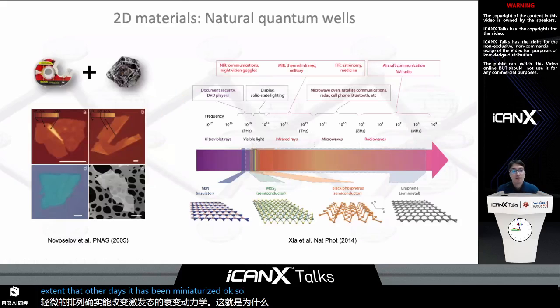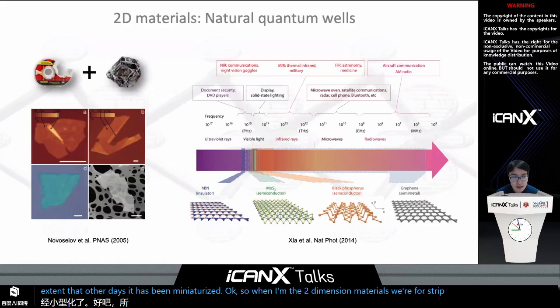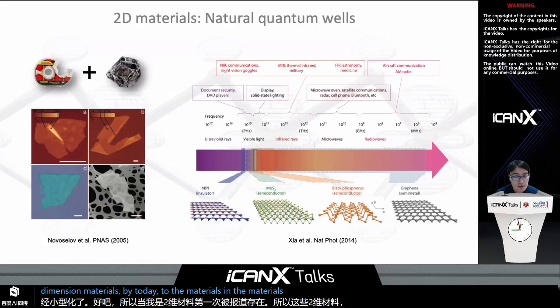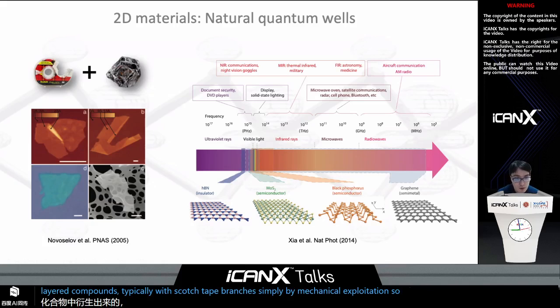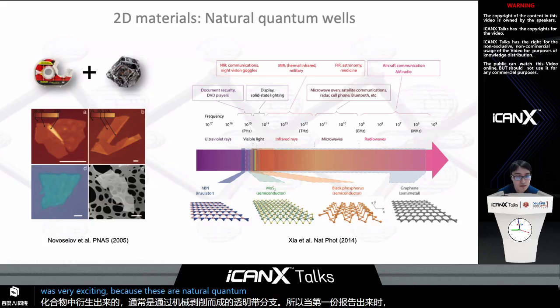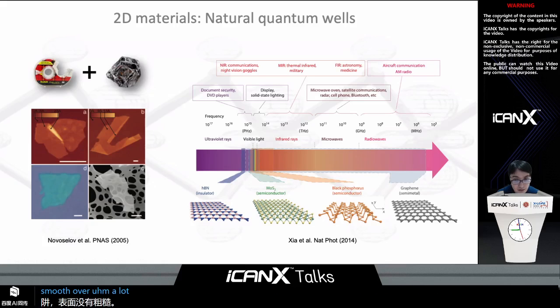So when the two-dimensional materials were first reported to exist, these two-dimensional materials, by 2D materials, I mean atomically thin materials that are derived from van der Waals layered compounds, typically with Scotch tape, simply by mechanical exfoliation. When the first report came out, it was very exciting, because these are natural quantum wells which have effectively no roughness on the surface. They're atomically smooth over long length scales.